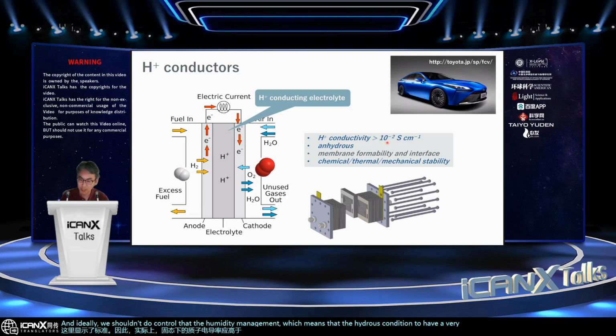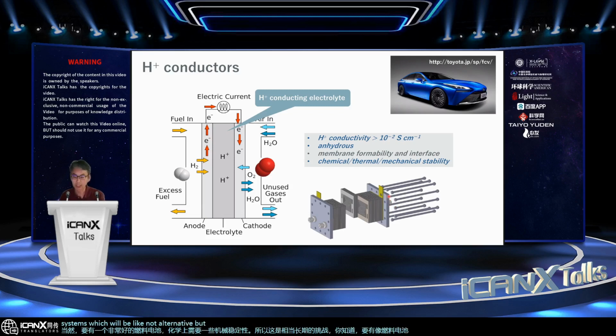in the solid state. And to make a very nice device, crystals actually have a very serious limitation in terms of fabricating the membrane. So real applications need membrane formability and good interface formability. And of course, chemical and thermomechanical stability is required for a very good fuel cell. So this is a quite long-term challenge, to have fuel cell systems, which will be not an alternative, but another contribution to the energy issues, as well as solid state lithium batteries.